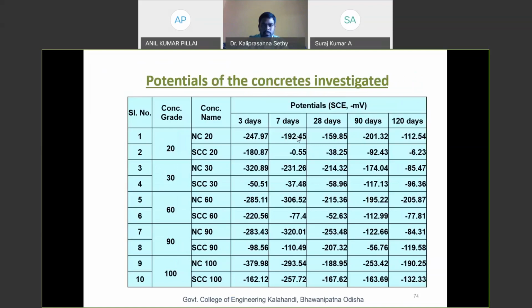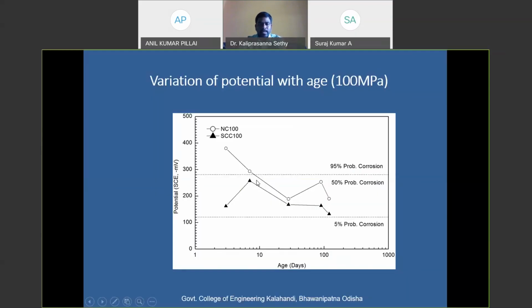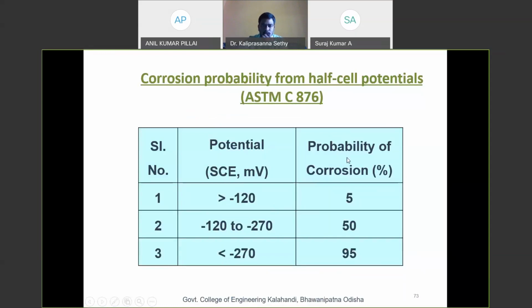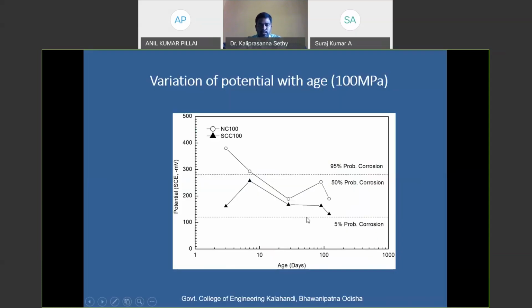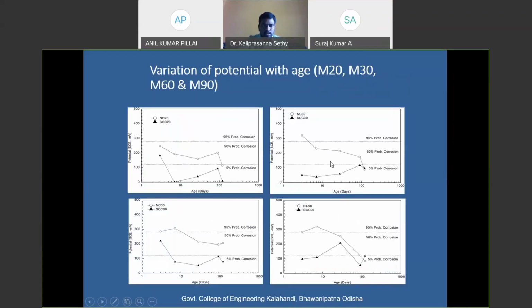Here is the test result of the potentials from 3 days to 120 days, and this is the graphical representation of all the concretes. As per the ASTM standard, the probability of corrosion is 5% if the potential value is greater than minus 120 millivolt, 50% for the middle range, and 95% if the potential value is less than minus 270. You can see from this diagram that for high strength concrete, that is M100, and for self-compacting concrete, the values are very near to 5%, and it is in the range of 50% probability. For other concretes, it is falling within the 5% probability of corrosion.